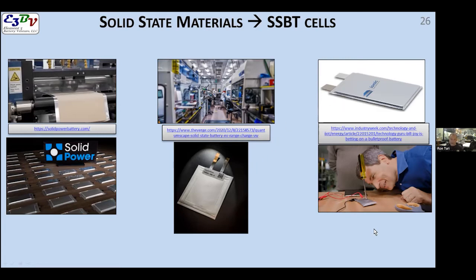And this is Ionic Materials, which has a polymeric solid state separator technology. They have polymer that conducts the ions pretty darn well. And all of these have pluses and minuses. This QuantumScape one uses a wafer ceramic made of LLZO, lithium lanthanum zirconium oxide, aluminum doped. So it's very specific and a hard material.